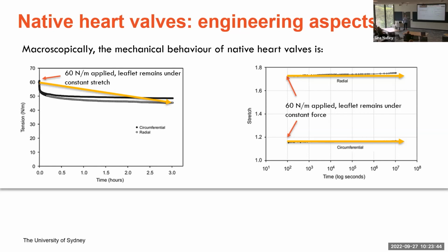But at the same time, when we deform or elongate them, they don't just keep elongating. When they reach a threshold, they just stay at that threshold. What it basically implies is that after billions of cycles, the size of the leaflets doesn't change, and at the same time, they can dissipate energy. So they don't really fracture, and there's no stress concentration, for instance.